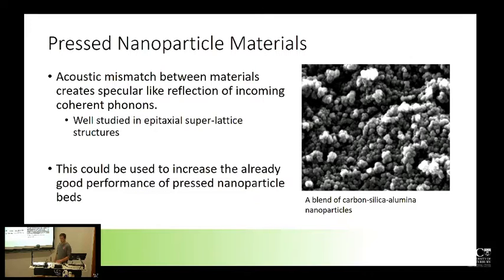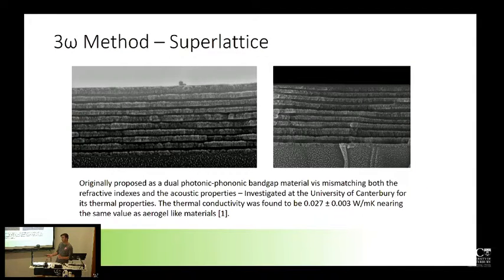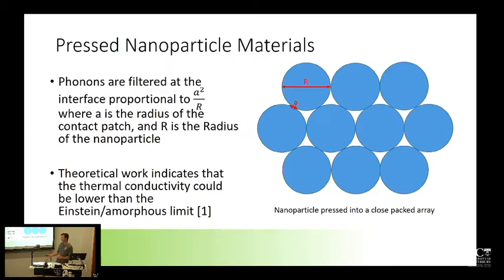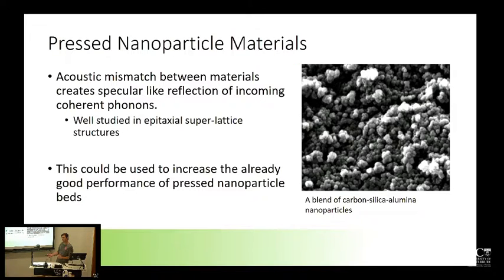But for the specular reflection, you must have quite a long wavelength in the phonons compared to the size of that structure. Compared to the size of this? Well, the other slide you had there, with all those nanoparticles. Yeah, the wavelength of the phonons must be a lot bigger than the size of those nanoparticles. The wavelengths of phonons in these materials are supposedly well represented by the bulk wavelength dispersion of phonons. So they are.